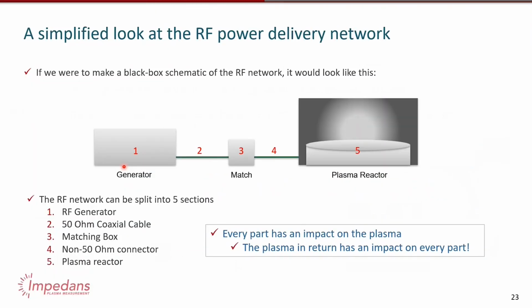It's not in here, but we actually have a document which is basically on how to use VI probes in a fab for troubleshooting, and it goes into a lot of detail on measuring at different points and what you can learn from measuring at different points. So for example, regarding reflected power, sometimes if you're just looking at the reflected power on the generator, or if your FDC system on your tool is only reporting 1 second, you can actually miss that during the initial ignition. You're getting a big spike in RF power, and that spike is getting larger and larger, and that's indicative of issues in the matchbox, right?